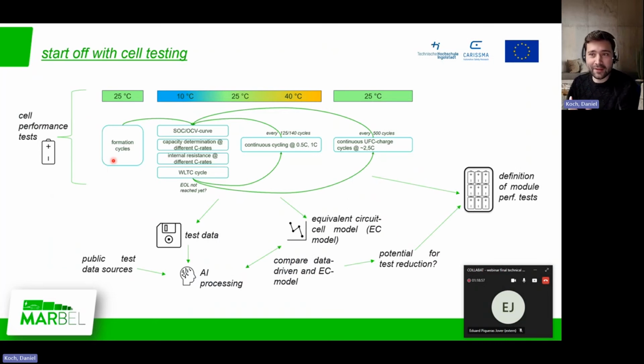Then, after getting the cells, we started off with cell testing, just as regular, I would say. We started with formation cycles and then the characterization at different temperatures to get input data for the cell models: on one hand for the AI data-driven models, and on the other hand for the equivalent circuit cell model. And then, in addition, we had continuous cycling to have some aging or degradation data of the cells. And as a second batch, we had continuous ultra-fast charging cycles.